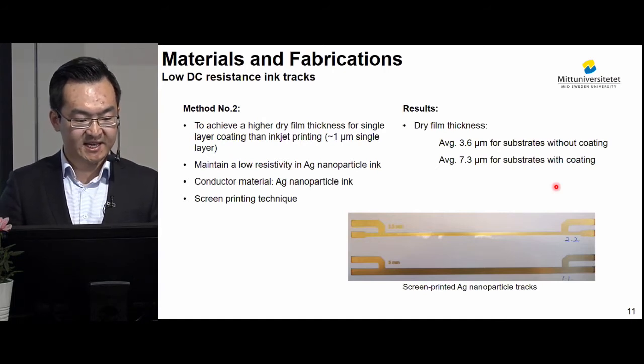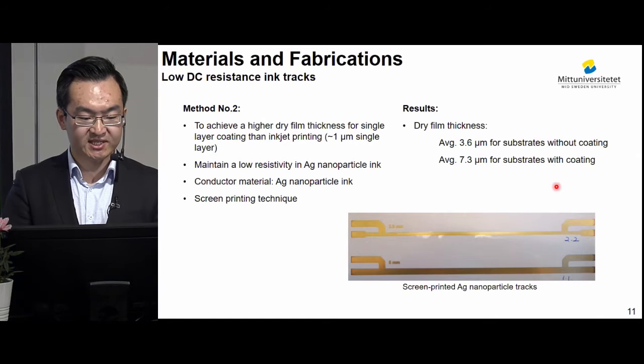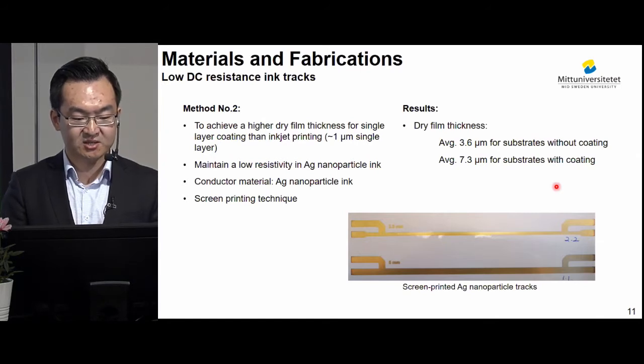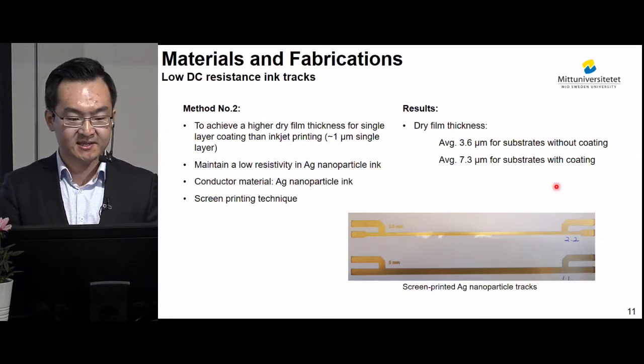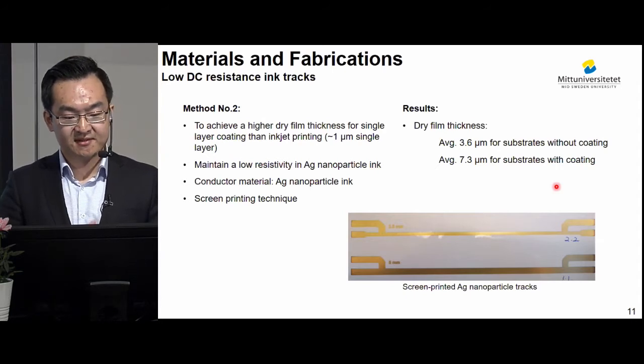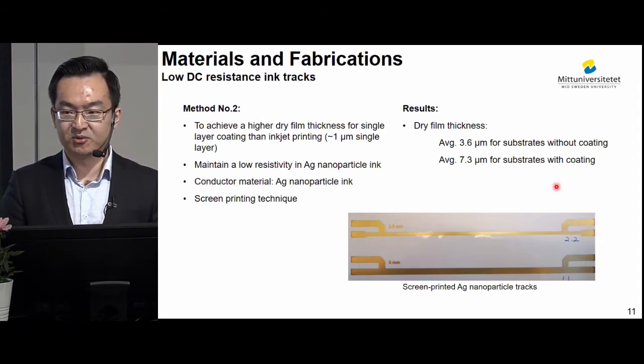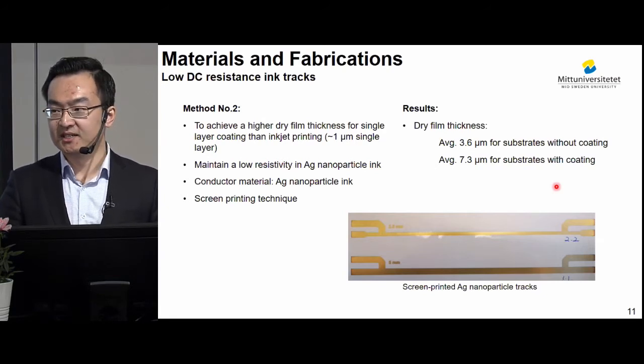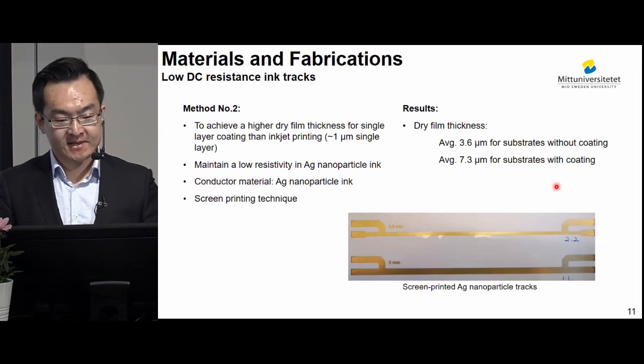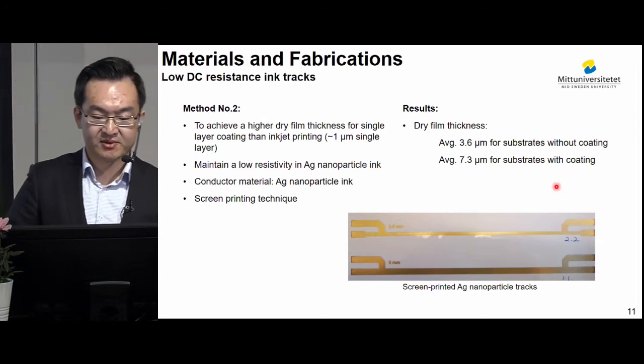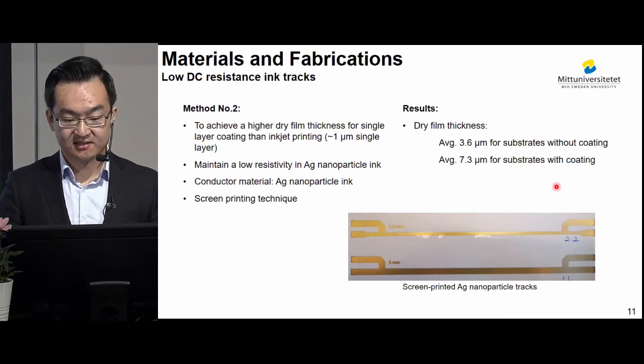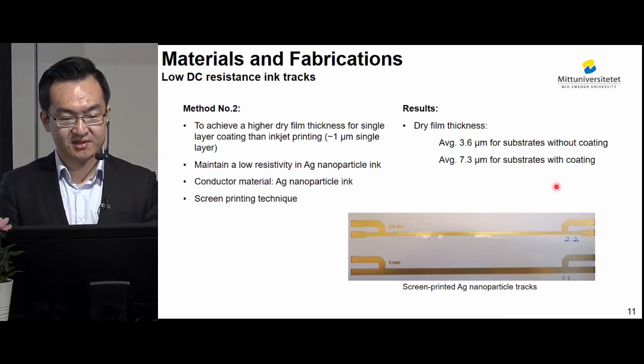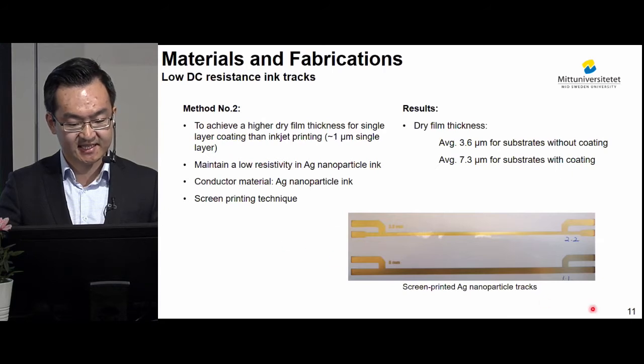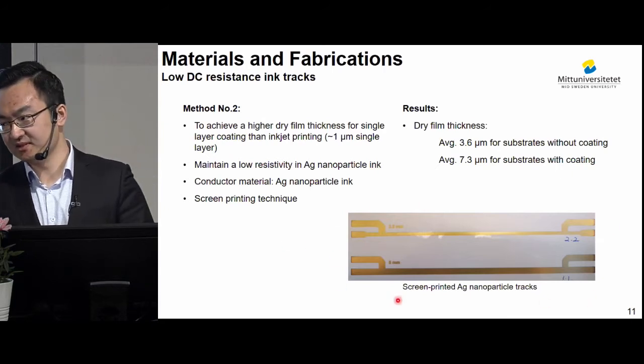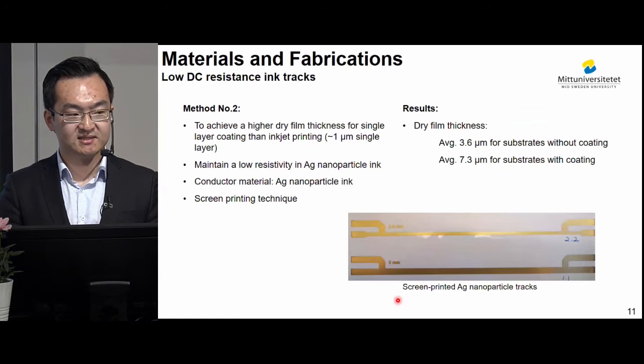And we have applied this screen printing technique with a silver nanoparticle ink onto different substrates, and the results showed that an average of 3.6 micrometer dry film thickness was achieved for substrates without coatings, and an average of 7.3 micrometer for substrates with coatings. And this is an example of the tracks made from this fabrication method.